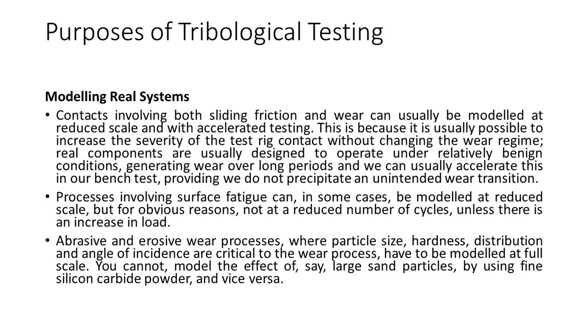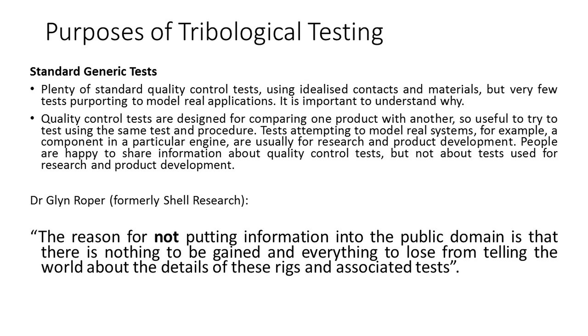Processes involving surface fatigue can, in some cases, be modelled at reduced scale but not at a reduced number of cycles unless there is an increase in load. Examples include rolling contact fatigue and fretting. Abrasive and erosive wear processes where particle size, hardness, distribution, angle of incidence, and particle velocity are critical have to be modelled at full scale. You cannot model the effects of large sand particles by using fine silicon carbide powder. There are plenty of standard tests for quality control using idealised contacts, but very few tests purporting to model tribological contacts in real applications.